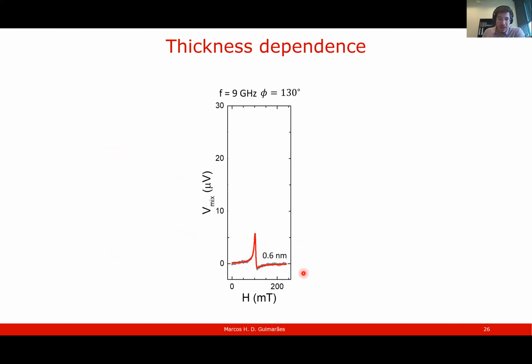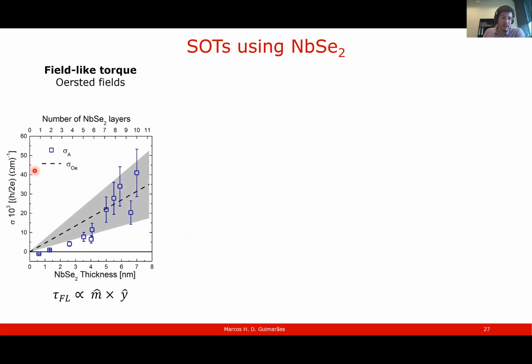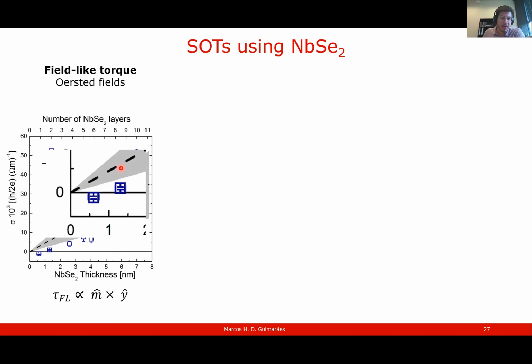So we did a thickness dependence going from monolayer, bilayer, 4 layers, and so on and so forth. And then we can map the torque intensity as a function of the thickness of the niobium diselenide. We start with a simple Oersted field-like torque, M cross Y. And this dashed line here is what you would expect from the Oersted field torques from the current flowing through the niobium diselenide. But if you look closely, for a monolayer and bilayer, they fall significantly below our error margin. And for monolayer, even points in the opposite direction. And this is a strong indication that these torques are actually coming from the interface between the niobium diselenide and